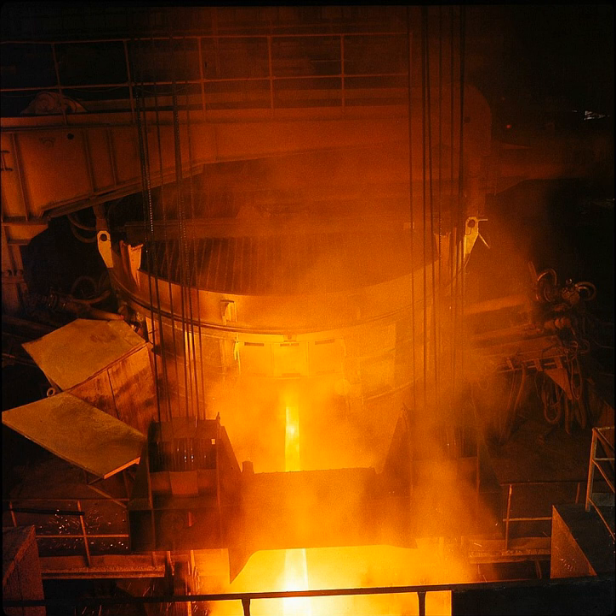Later in the heat, carbon in the form of coke or coal is injected into this slag layer, reacting with the iron oxide to form metallic iron and carbon monoxide gas, which then causes the slag to foam, allowing greater thermal efficiency, and better arc stability and electrical efficiency. The slag blanket also covers the arcs, preventing damage to the furnace roof and sidewalls from radiant heat.